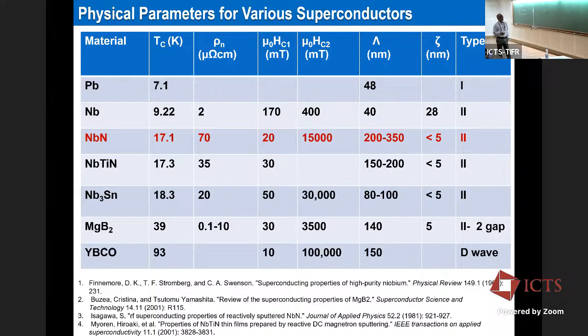Then there is the high lower critical field of Nb, which is a very good feature from an application point of view. As you can see, you can have a full Meissner state in a wide range of the superconducting phase diagram. So that gives you a better thing. And then you have a short penetration depth. This indicates that there is a very thin skin of superconductor into which the magnetic field can penetrate, right? So these are the advantages of Nb.